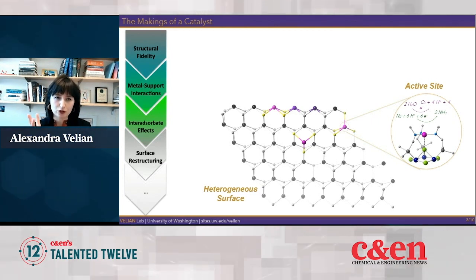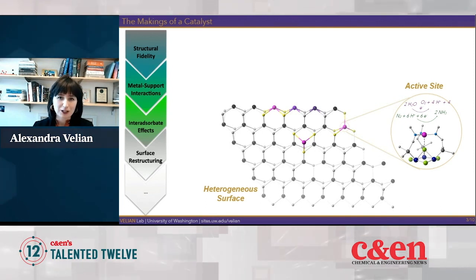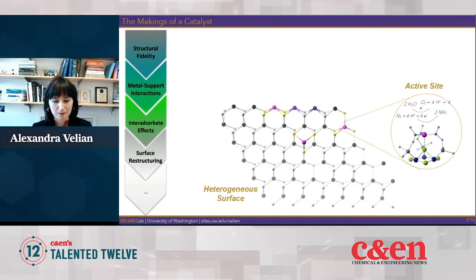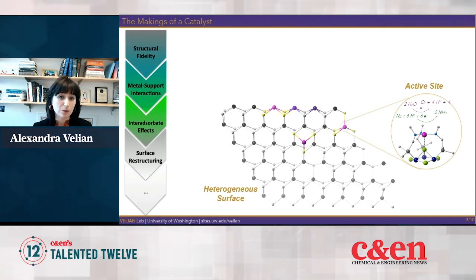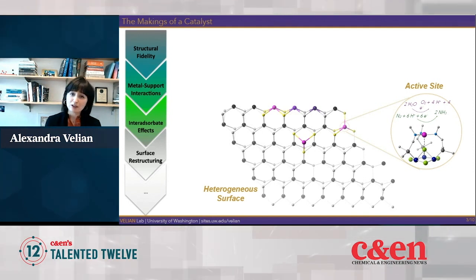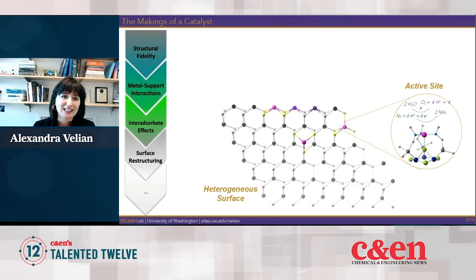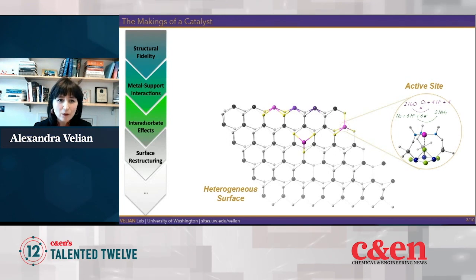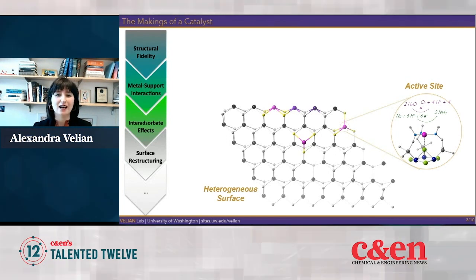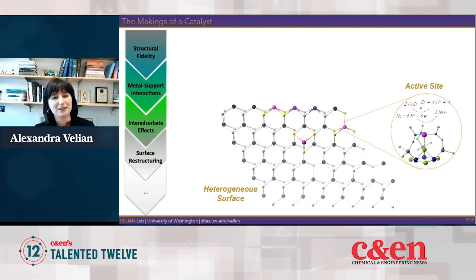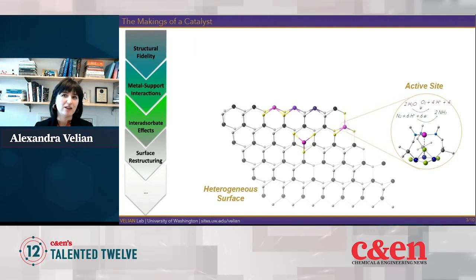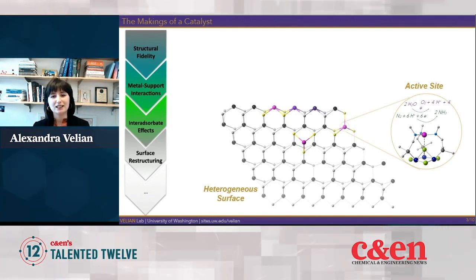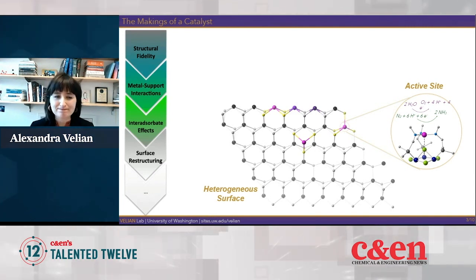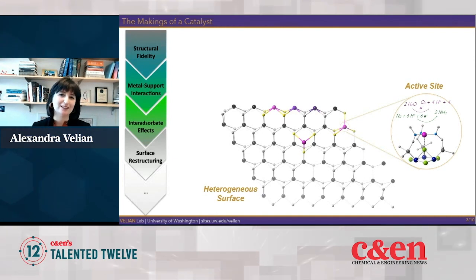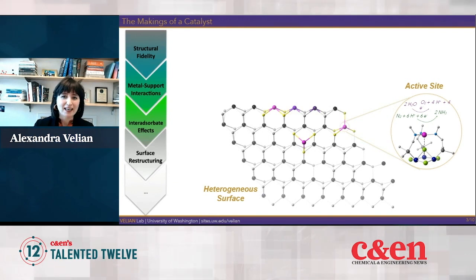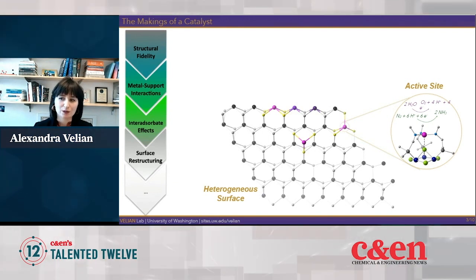And so if we are to achieve structural fidelity across the active sites, an orthogonal strategy is to synthesize single-site catalysts essentially by anchoring metal centers onto supports. And in my group, we are interested in those supports that are chemically non-innocent and therefore can work synergistically with the metal to amplify its activity. Now, if we could synthesize such single-site catalysts with high structural fidelity, and if we could experimentally probe the metal support interaction or interface with atomic detail, then we could elucidate how factors underpinning this cooperativity, for example, metal support interactions, interadsorbate effects, surface restructuring, etc., can impact catalysis and use this knowledge to tune the resulting platforms.